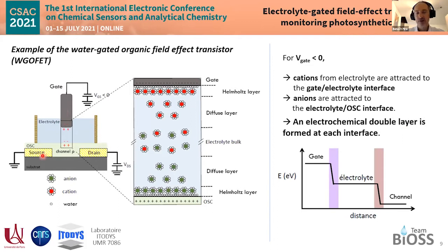between the gate and the source, and between the gate and the semiconductor, charges, that is ions from the electrolyte, will accumulate at the gate electrolyte interface and at the semiconductor electrolyte interface, forming the very well-known double layers, of course. But the capacitance of which being very large, the potential drop at the gate electrolyte and electrolyte channel interface are usually very large in this configuration, so that they can work at very low voltages, around 1 volt, or even a few hundreds of millivolts instead of several tens of volts for more classical transistors.